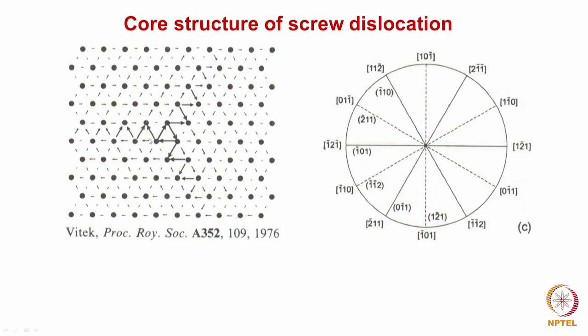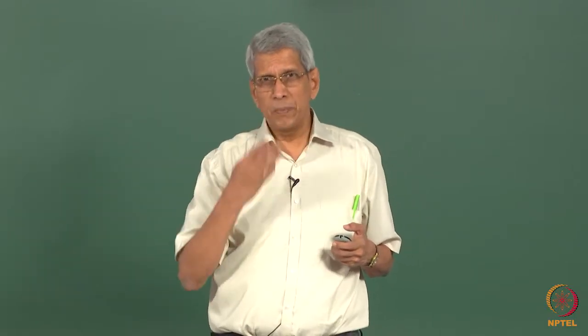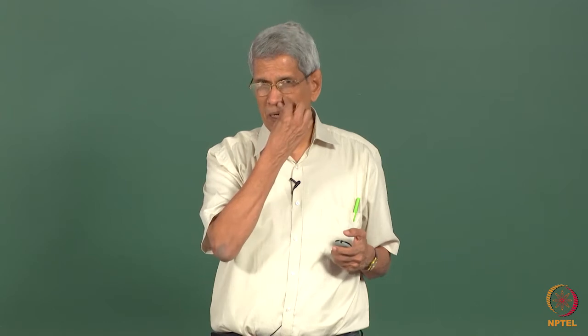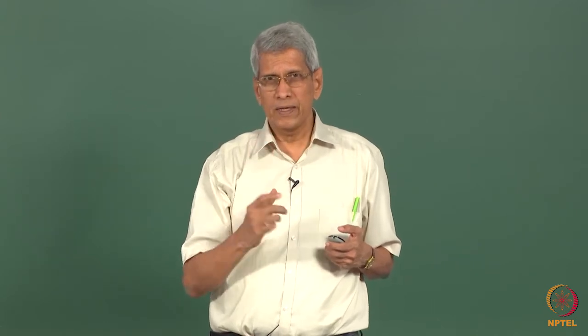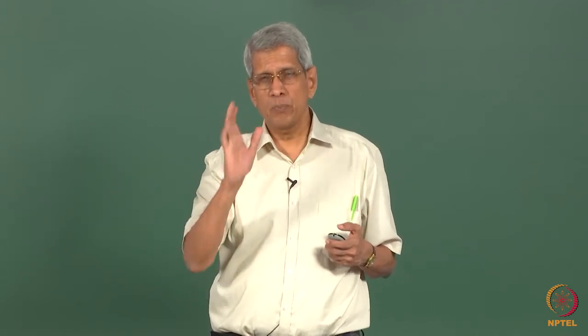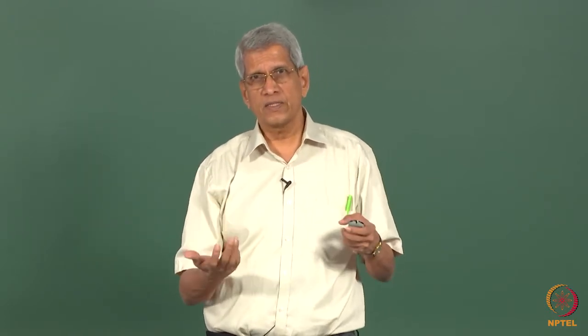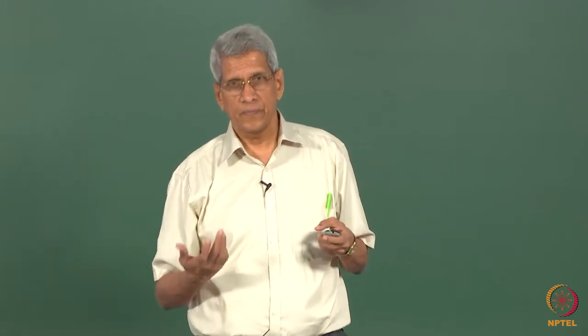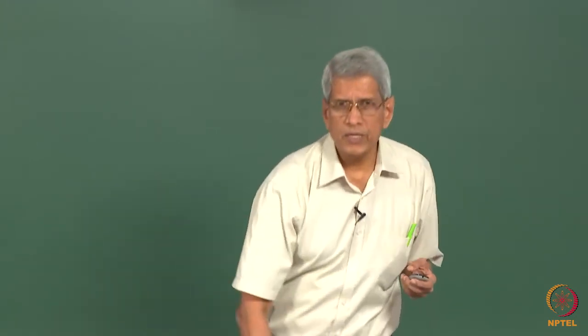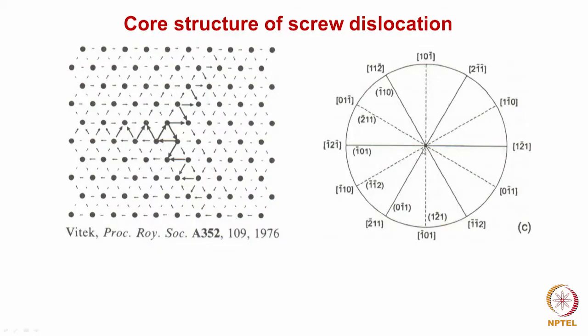So essentially the displacement around a screw dislocation, that is around the core of the dislocation, has split on 3 110 type of planes, which contains the dislocation. This figure that we are showing is a stereogram, and the stereogram shows the various directions. This is 111, 112 type of a direction, and this is the plane. In this plane it will contain.